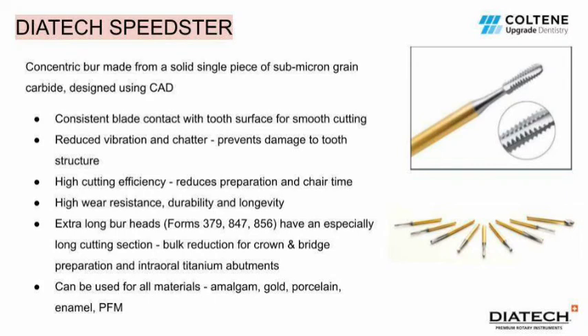DIATECH Speedster burrs are concentric burrs made from a solid single piece of submicron grain carbide designed using CAD. They result in a consistent blade contact with the tooth surface for smooth cutting. There is reduced vibration and chatter, which prevents damage to tooth structure. They have a high cutting efficiency, which reduces preparation and chair time, and a high wear resistance, resulting in durability and longevity. The burr heads are extra long and have an especially long cutting section, which makes them useful for bulk reduction of crowns and bridges during preparation and intraoral titanium abutments. They can be used to cut all types of materials, including amalgam, gold, porcelain, enamel, and PFM.